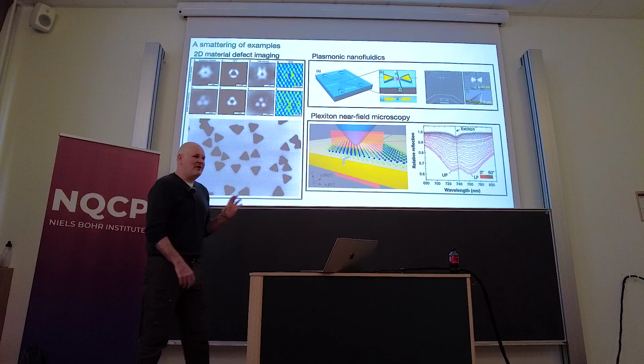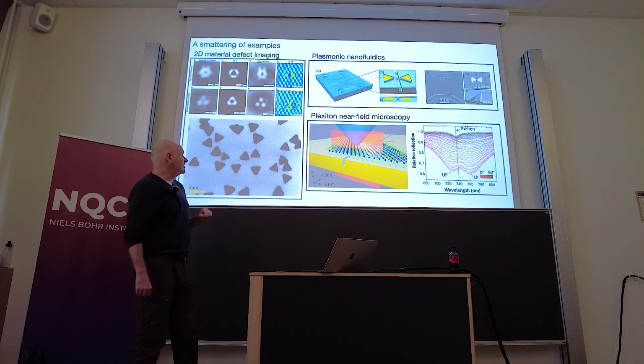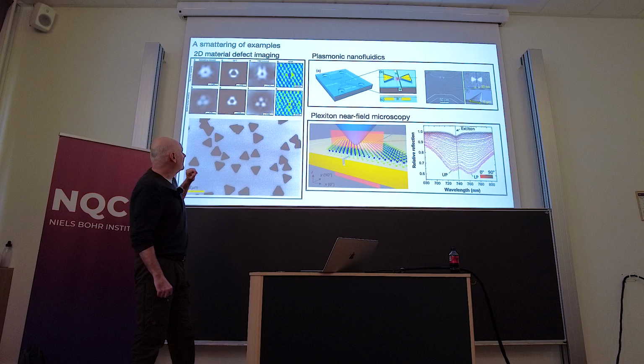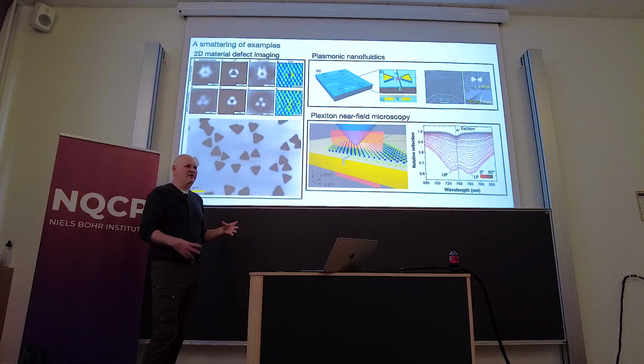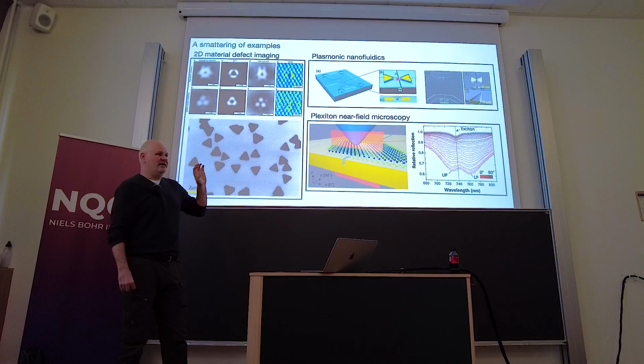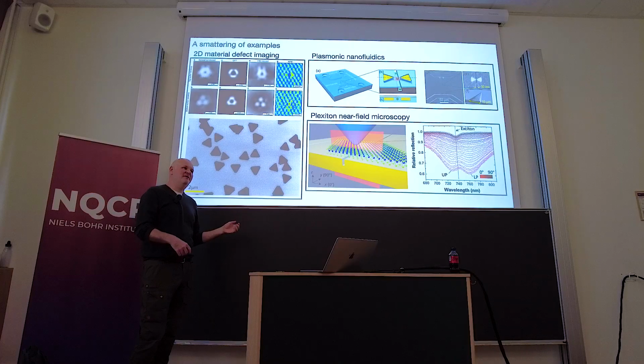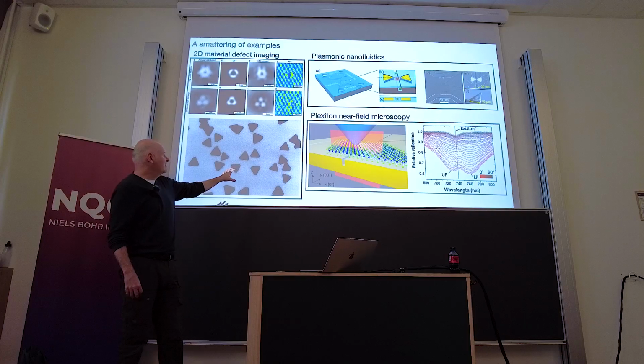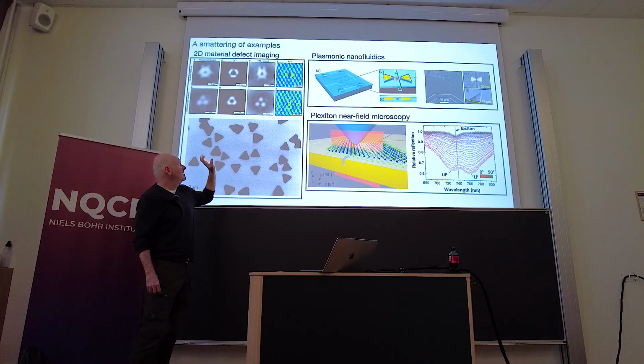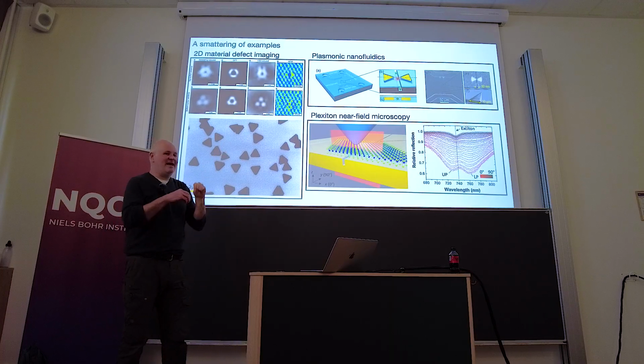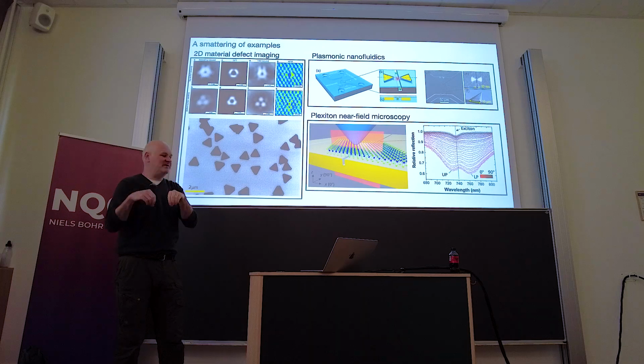So I know probably quite a few people here are familiar with 2D materials. We also did work on 2D materials. We developed a fairly unique process by which to grow tungsten disulfide and other disulfide materials, where we would grow atomic layer deposited transition metal oxide films and then use them as precursors in a tube reactor to grow the crystals. So these are single crystals that we grew onto a substrate, and then we handed these off to my colleague Alex Weber-Bargioni, who did STM measurements and was looking at individual defects in those TMD materials.